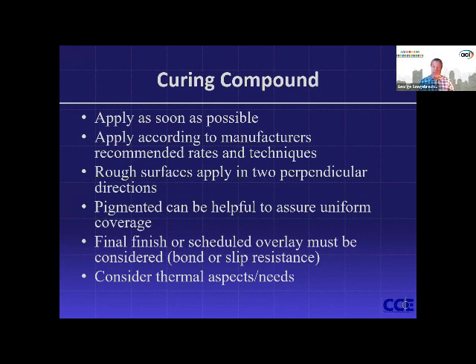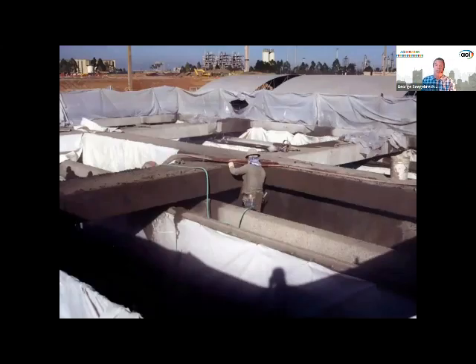Again, watch out for what's going to be happening afterwards. And then again, this does not have any thermal benefit. A job that I worked on in LA County for their sanitary district, curing. Boy, it was so hot, and shotcrete mix is relatively rich. It is rich. And drying conditions were just all over. They really fought against this and did a very good job. Wind breaks and immediately covered things as soon as possible.